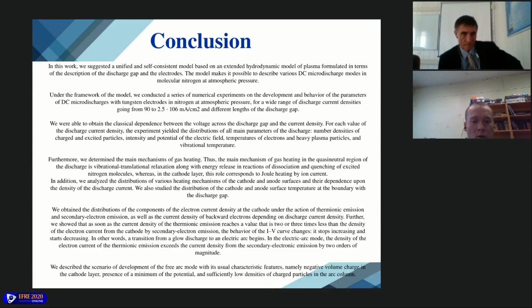Thus, the main mechanism of gas heating in the quasi-neutral region of the discharge is vibrational-translational relaxation, along with the energy release in reactions of dissociation and quenching of excited nitrogen molecules. We obtain the distribution of components of the electron current density at the cathode under the action of thermionic emission and secondary electron emission, as well as the current density of backward electrons depending on the discharge current density.